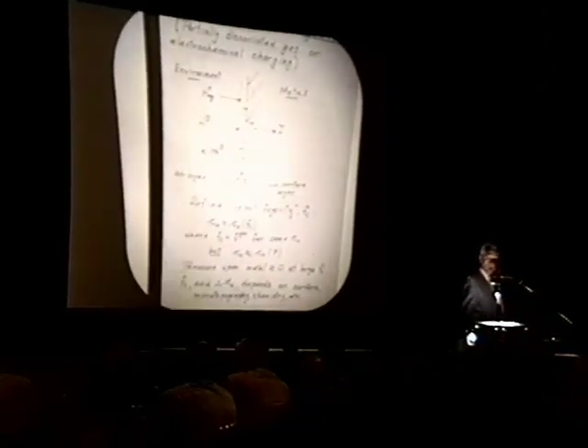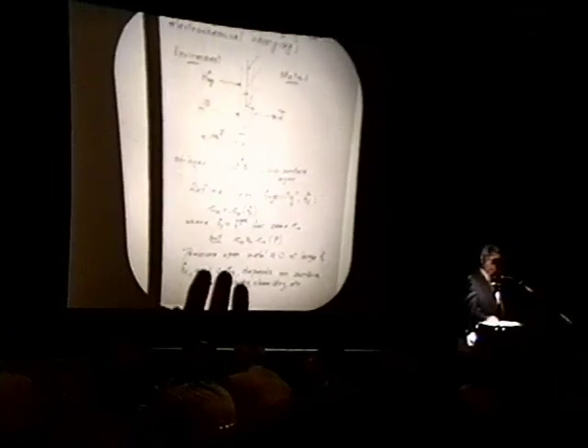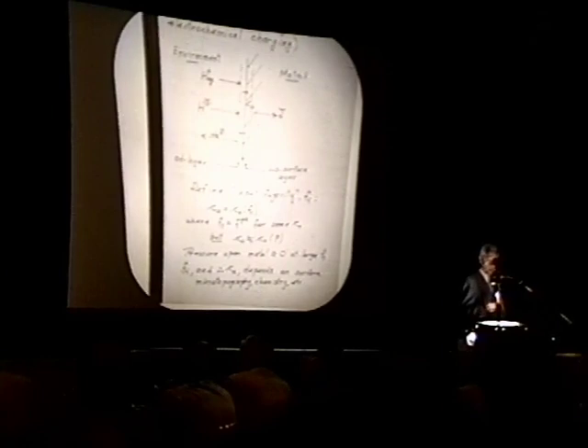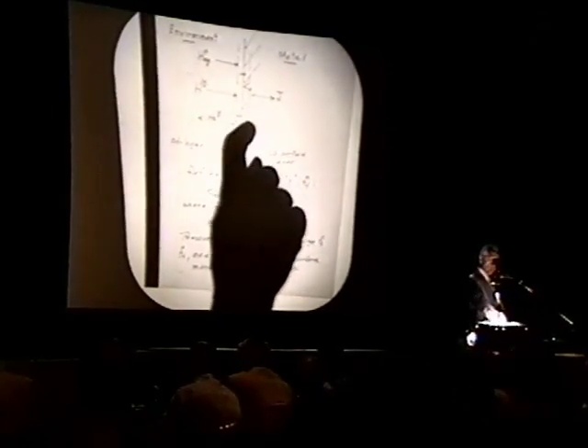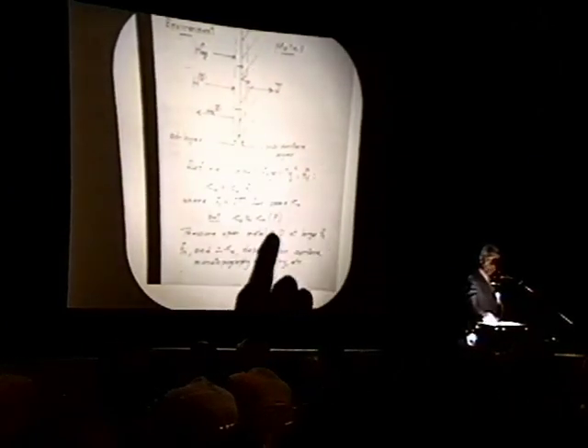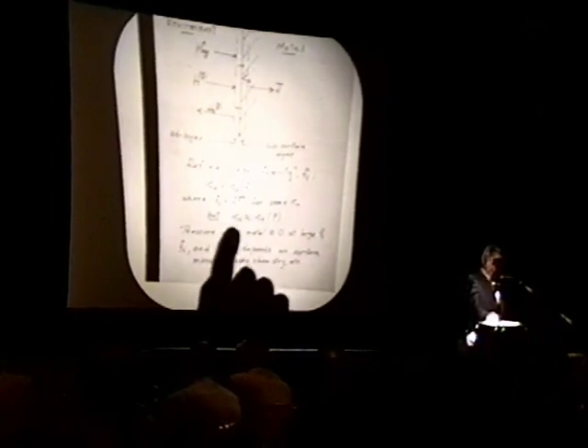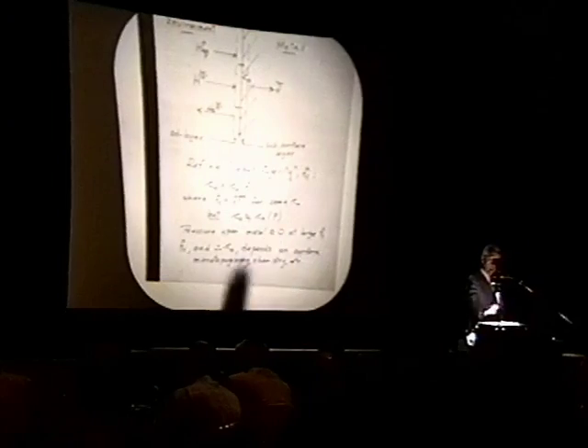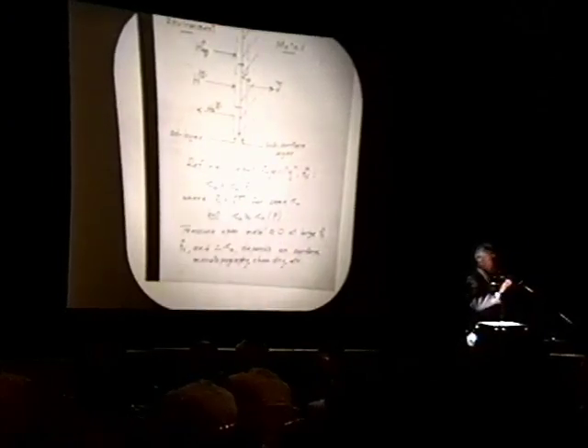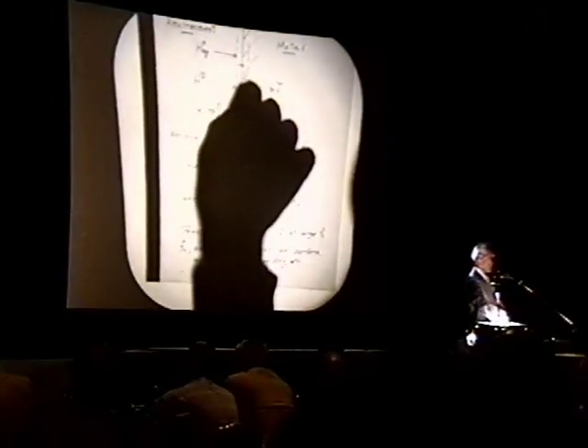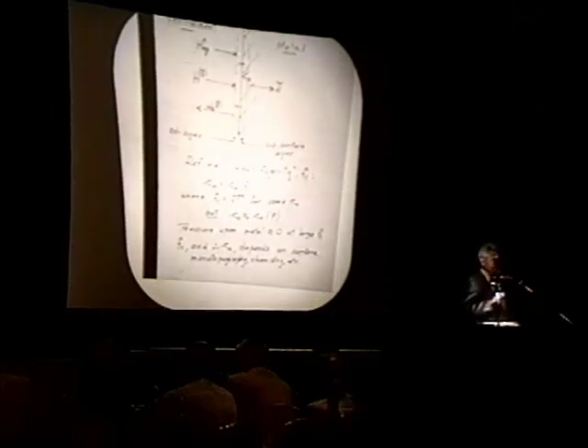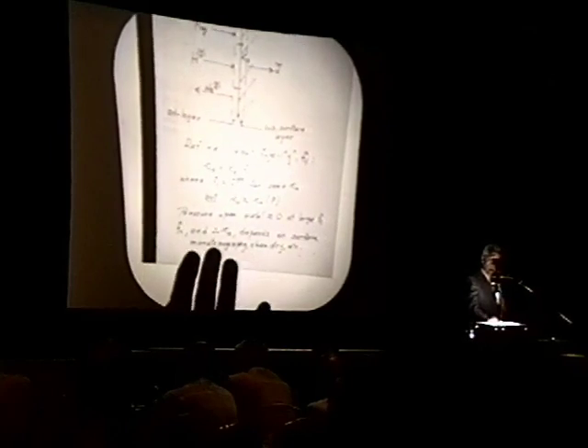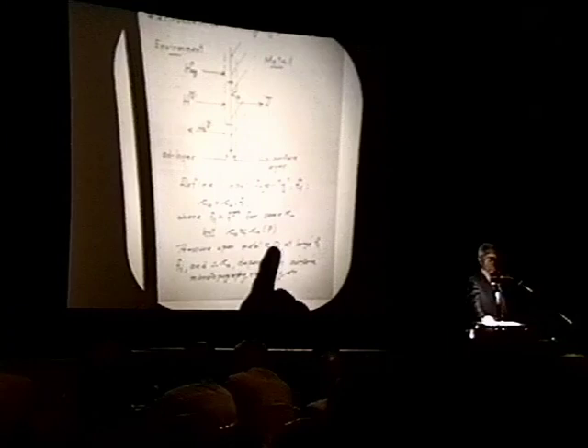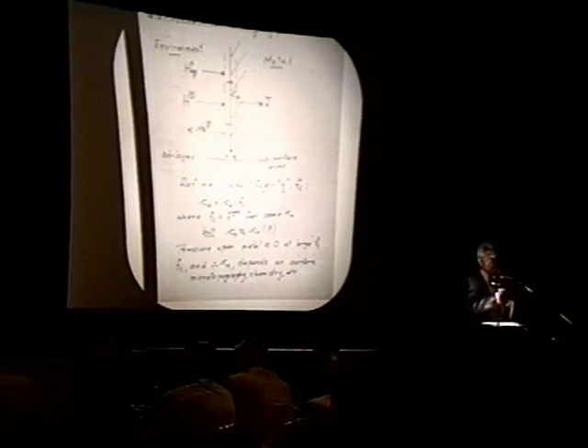In the case of cathodic charging, the adsorbed population is controlled by competitive kinetics. However, we like to define what we call an input fugacity or effective fugacity, such that the C0 that controls the subsequent diffusion inwards is in fact a function of that input fugacity. And we will say that the input fugacity would be the same as the fugacity in the molecular gas charging which gives the same C0 in here. Now that input fugacity is a totally kinetic quantity, cannot be calculated in thermodynamics, and it is not associated with the hydrostatic pressure. As I indicated before, when you input hydrogen into the metal, the lattice expands, the outer surface goes out farther than the internal surface around it.